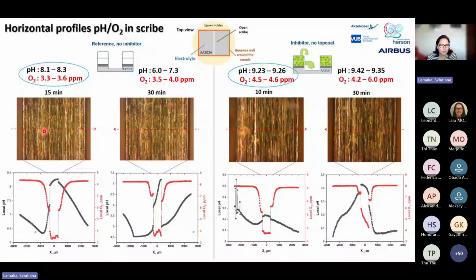And for oxygen concentration, indeed, we see a very high concentration of oxygen remaining at the aluminum interface in the scribe, because oxygen reduction kinetics is slow due to the layer of inhibitors that builds aluminum lithium hydroxide. But for the reference sample, we observe strong depletion of oxygen due to active corrosion process.